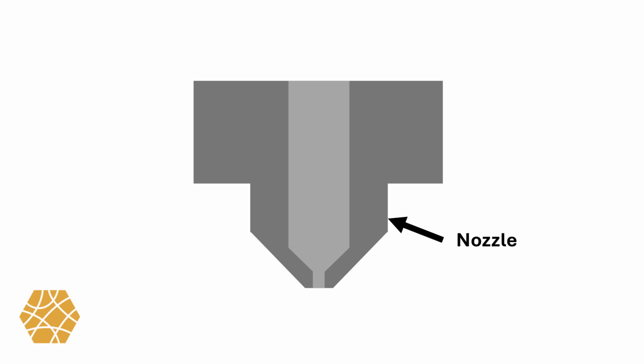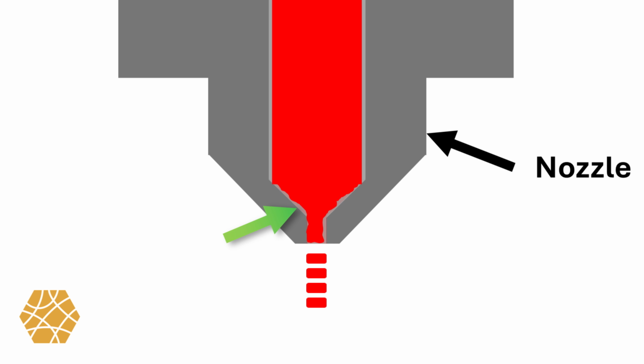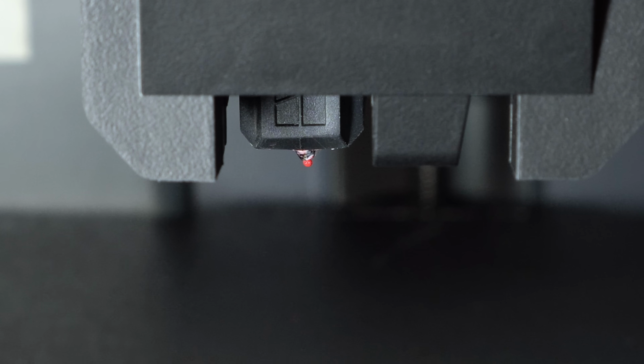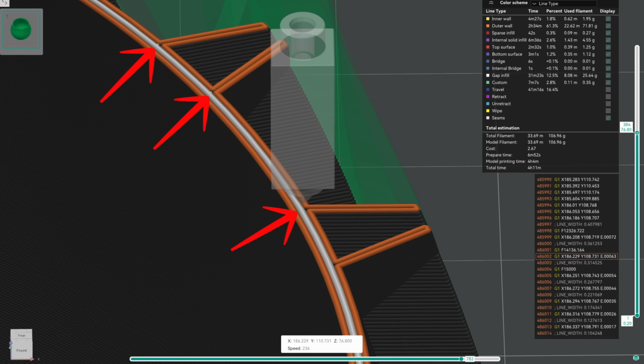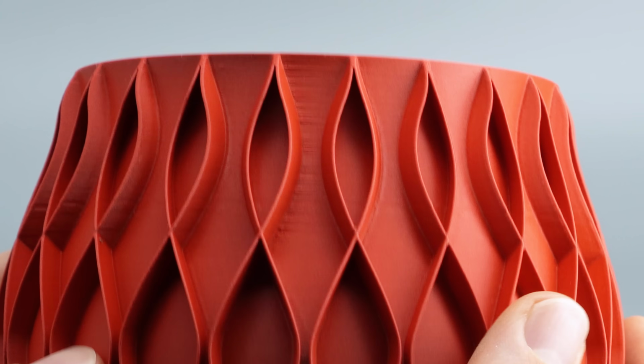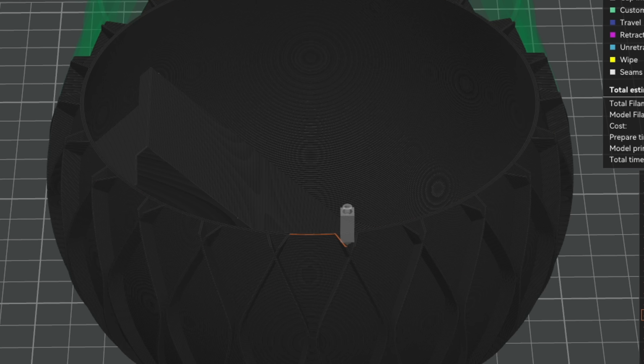Let's quickly understand why. Tiny extrusions lead to retracting filament out of the nozzle and then pushing it back in for just a moment over and over again, only extruding a tiny bit, but not enough to keep up nozzle pressure. And worse, may even empty it completely due to oozing. So after these tiny dots here, we have very low nozzle pressure and an extremely ugly next print line in return, which is the first wall of the next layer for this test print.